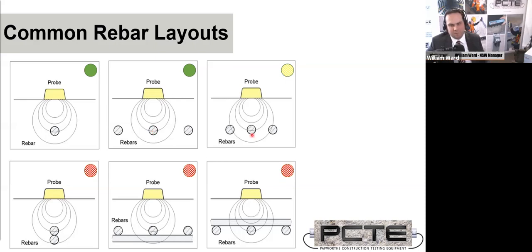If you have parallel bars closer than 150 millimeters, but your perpendicular bars are still sufficiently distant, you can use your neighboring rebar correction. If you've got perpendicular bars, the Profometer also has a neighboring rebar correction for those as well. You've got quite a lot of adjustment on a Profometer. The Profoscope is limited to a single assumed spacing between both layers of both directions of bar.